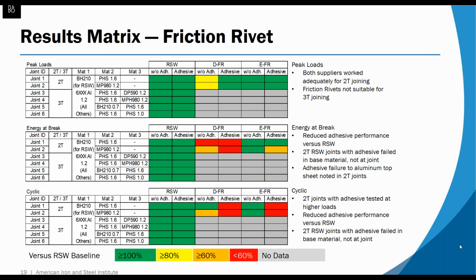And this is the tabulated data. In general, the friction rivet worked well for two-thickness joining for peak loads. We did see some reduction in energy absorption depending on the size of the interlock with the joining element and how much energy it took to tear through the top sheet. In the case of cyclic loading with adhesives, because the failure mode changed from the top sheet to the interface, we saw some reduction in performance there.